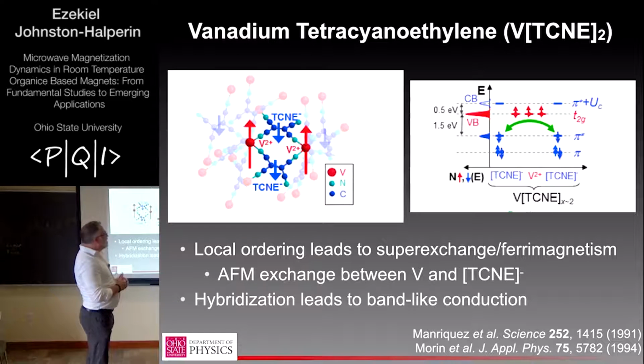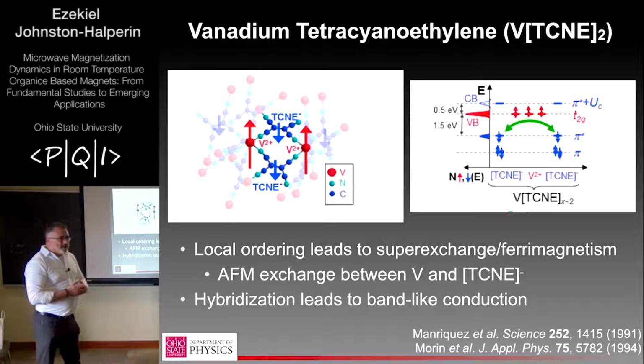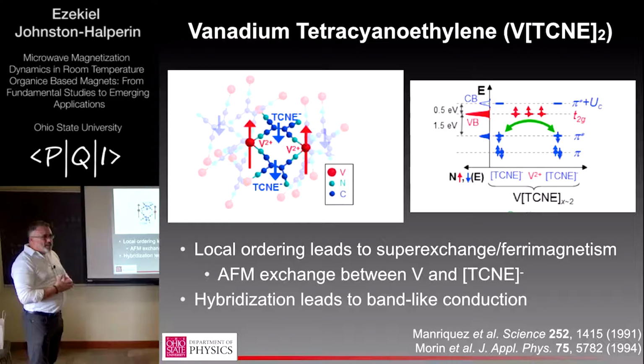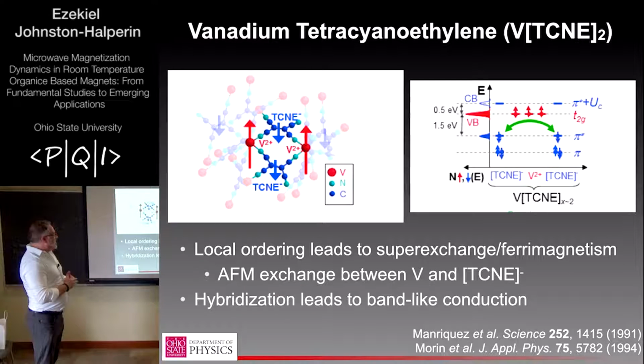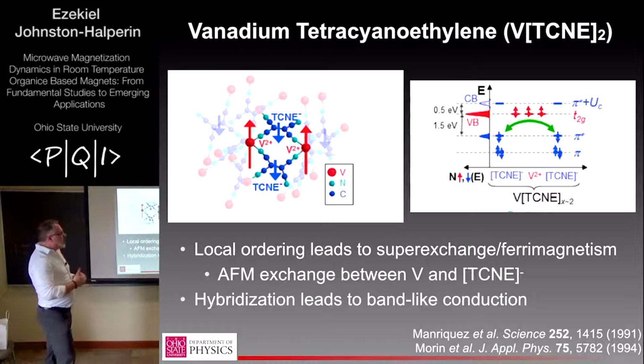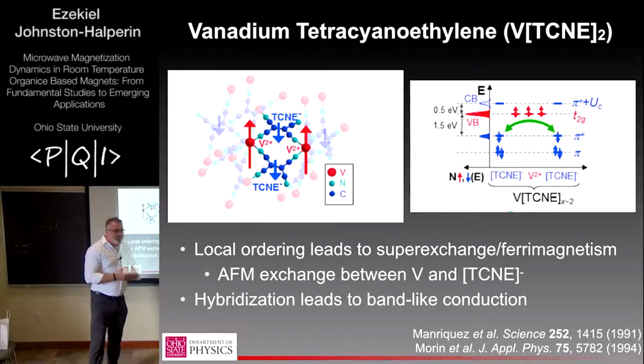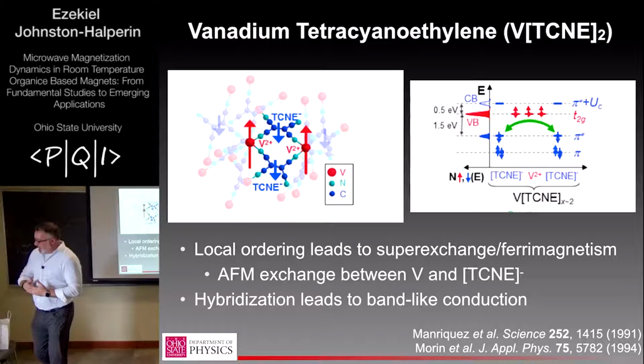Why isn't that thing Jahn-Teller to start? It's got all that degeneracy. So usually when things have degeneracy, there's a possibility of distorting via the Jahn-Teller effect and removing the degeneracy. The t2g with the three spins on it: why are those three spins still energy degenerate? Why isn't Jahn-Teller starting and doing something large in energy?